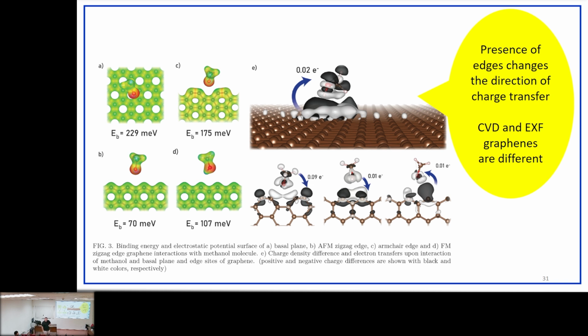Please. For chemically exfoliated graphene, the Raman spectra are very clear for that. Not only do you have plenty of small grains and boundaries and so on, you must probably also have oxygen functional groups, for sure. So my question is, perhaps you should take this point into account. Chemically exfoliated graphene has plenty of disorder, oxygen functional groups and so on, that may also have a role besides the size of the graphene grains. Yeah. So far we didn't consider that scenario, but maybe you are right.